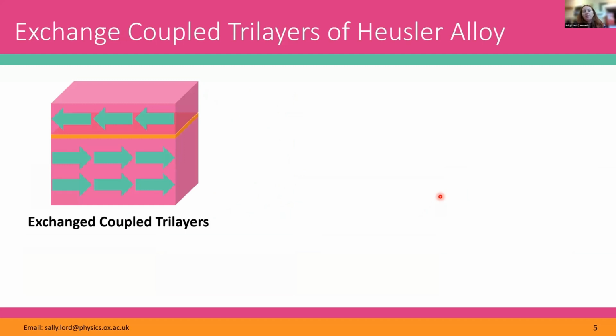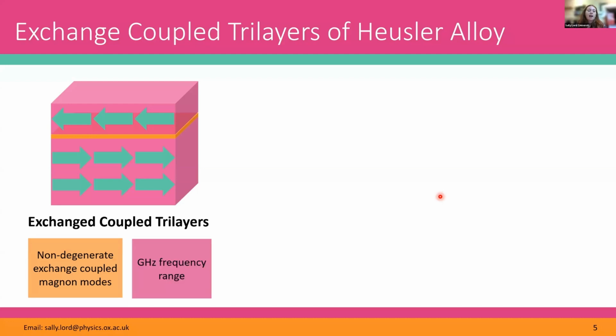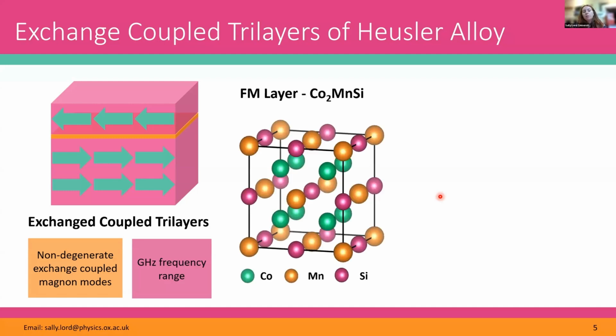So exchange-coupled trilayers consist of two ferromagnetic layers with an interlayer sandwiched between them, and by controlling the thickness of the interlayer, you're able to control the coupling between the two ferromagnetic layers. So for certain interlayer thicknesses, you're able to excite two non-degenerate exchange-coupled Magnon modes, and these have frequencies in the gigahertz range. But obviously, this type of material is only useful for Magnonic applications if you have a good choice of ferromagnetic material.